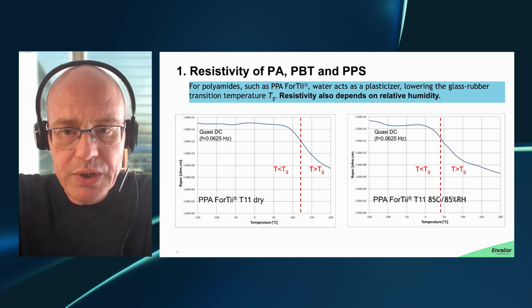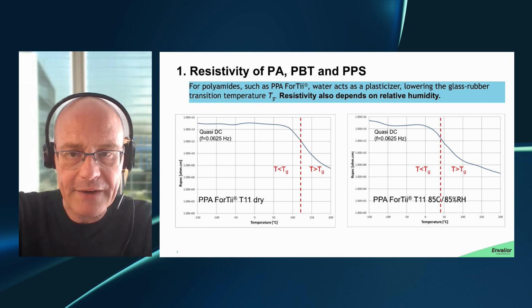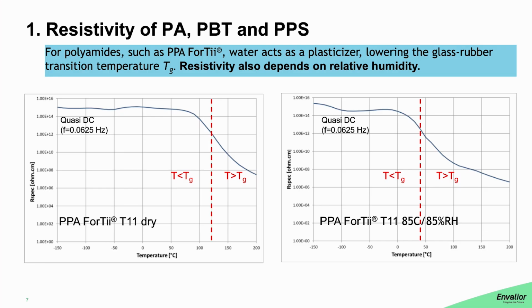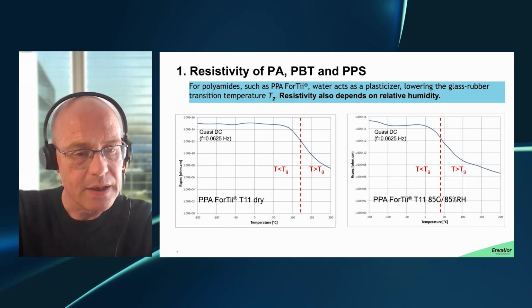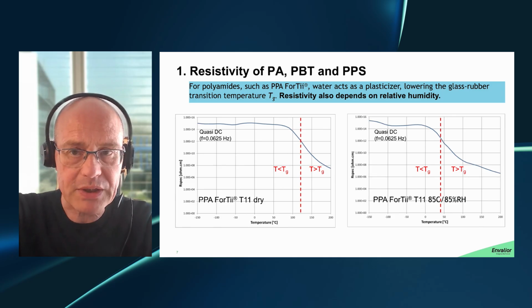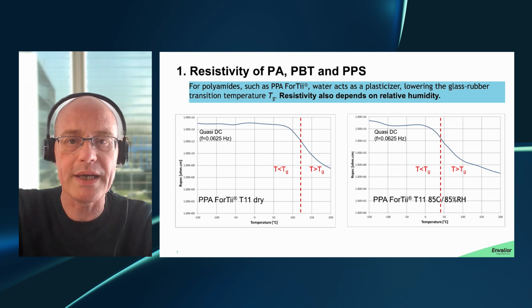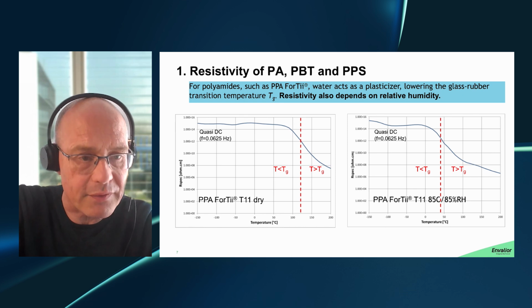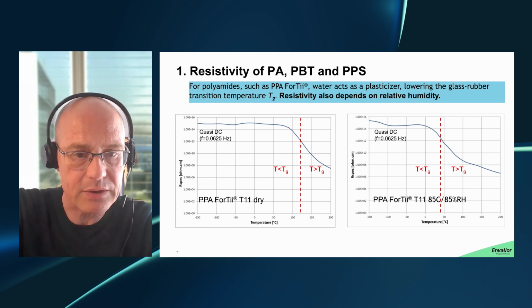Maybe more precisely, what you see in the picture on the left is the dry PPA has a glass transition temperature at around 120. You see that if the polymer picks up water at 85% relative humidity, Tg drops to around 40 degrees Celsius, and therefore this transition from glassy electrical response to rubbery electrical response is now shifted. So clearly what you see from these pictures is that resistivity is also a strong function of the relative humidity. So temperature and relative humidity.